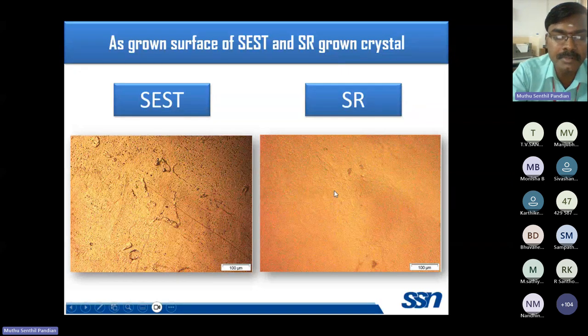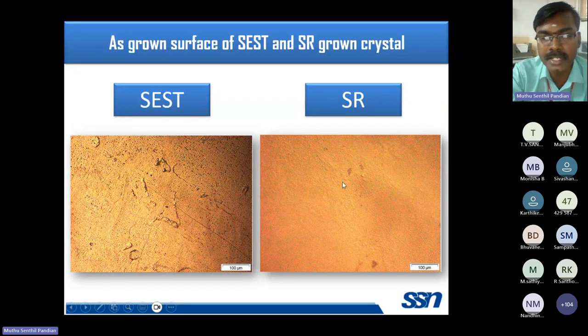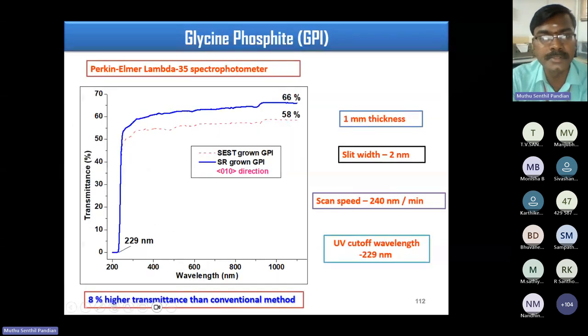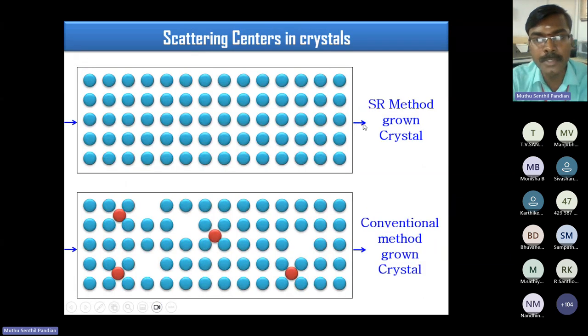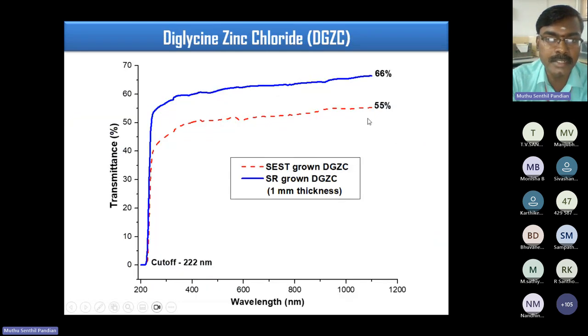But in the case of the SR method grown crystal, there is no solvent inclusion, micro cracks, or milky opaques, and less dislocation density. The surface is smooth compared to the conventional method grown crystal, which causes the higher output intensity and the higher optical transmittance in the SR method grown crystal. You see, 8% higher optical transmittance appeared for the SR method grown glycine phosphite single crystal compared to the conventional method grown one because of the higher output intensity. But in the conventional method grown crystal, a large number of scattering centers cause the low output intensity and the low optical transmittance.